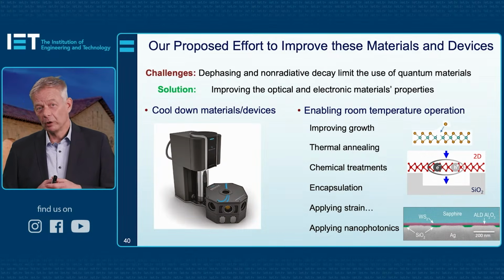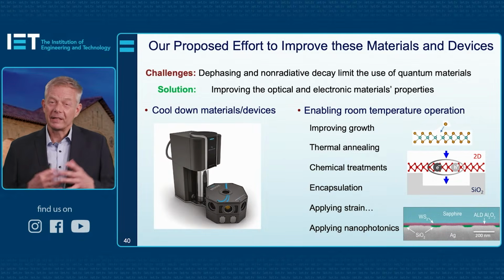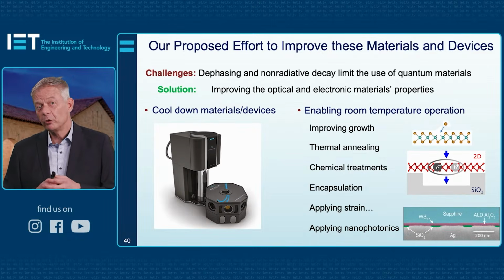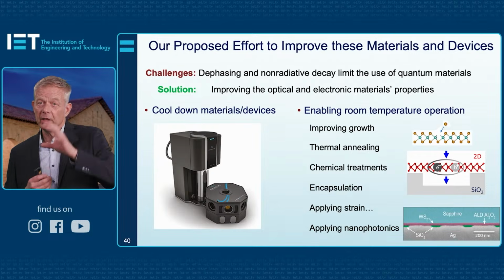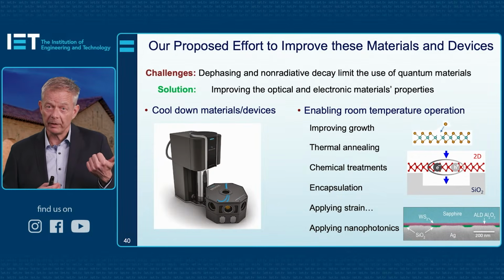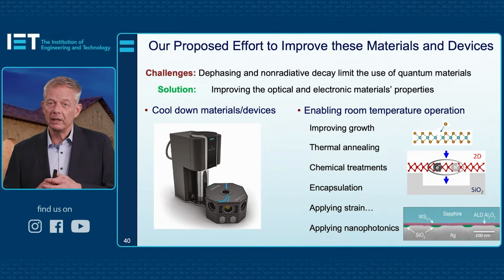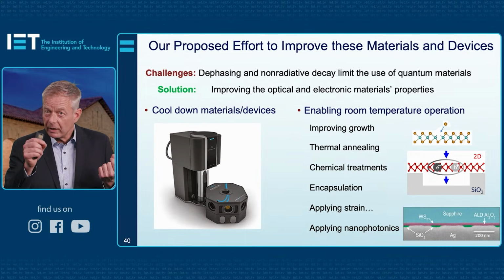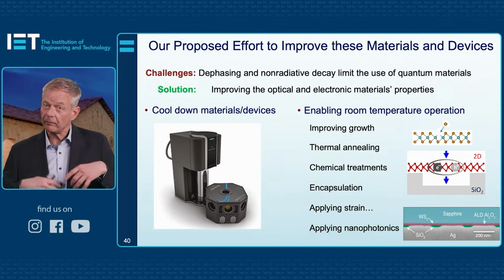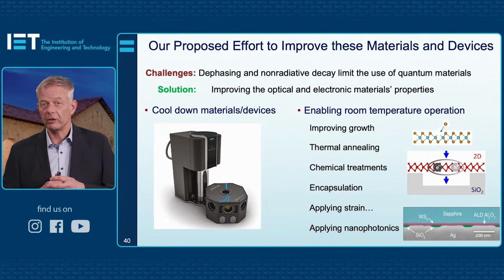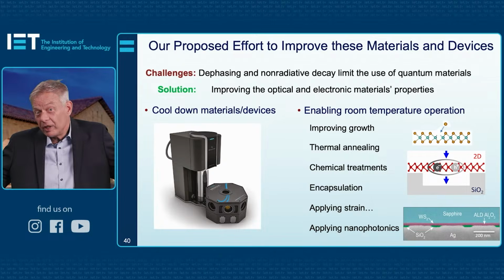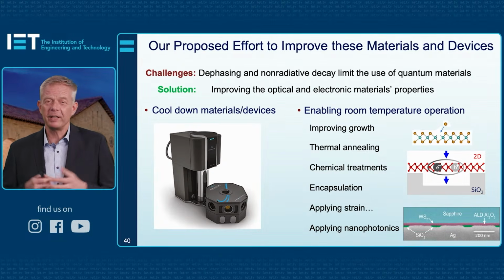But we have solutions, and there's a large materials team of physicists and engineers working on this to not only go to low temperature and see this, but to enable room temperature operation by improving the growth of these materials, by heat treating them, thermally annealing them. Chemical treatments can place atoms that were missing in these materials back in and make them more efficient reflectors and scatterers of light. We can encapsulate them to protect them from the environment. We can stretch them to change their optical properties, and we can apply one of our favorite topics, nanophotonics, for example, bringing in metallic structures close by these 2D materials to enhance the light-matter interactions, for example, using plasmons.